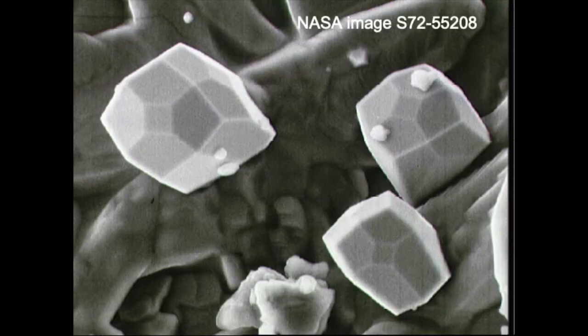These iron crystals are very small — you can only see them using techniques such as scanning electron microscopy. They are of the order of one micron in size, far less than the width of a human hair. Even in the early 1970s, those chemical analysis facilities were available in these microscopes, and they were able to establish beyond reasonable doubt that they were essentially pure iron crystals. You could argue there's a half a weight percent nickel, but it's essentially below the limit of detectability.